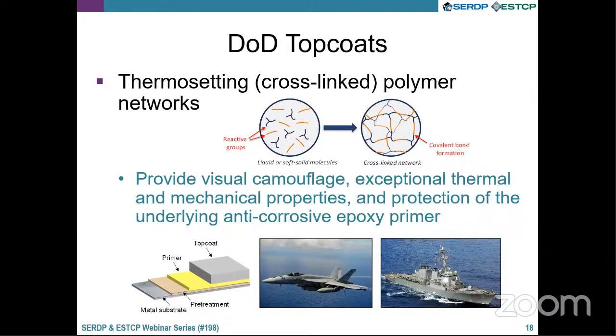And the reason why we use these thermosetting materials is because they provide very unique properties. Obviously, the main one is camouflage, right? Whether it's the picture of the aircraft or the ship below, we have some sort of a camouflage gray, or could it be green or brown or another color? But these thermosetting networks also provide exceptional thermal and mechanical properties, in addition to protection of our underlying anti-corrosive epoxy primer. Now, in the bottom left-hand side, I have a stack up showing what would be a metal substrate with a pre-treatment, a primer, and then a top coat, which typically on a lot of our assets is 50 to 70 microns thick. However, not all of the assets use a pre-treatment. That's typically relegated to mainly aircraft usage.